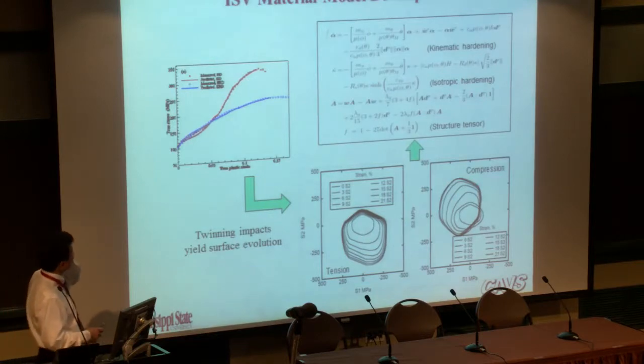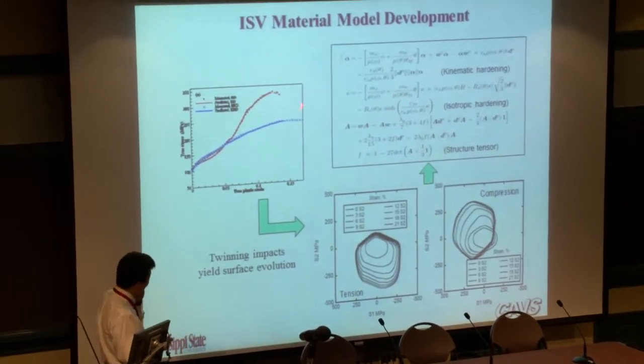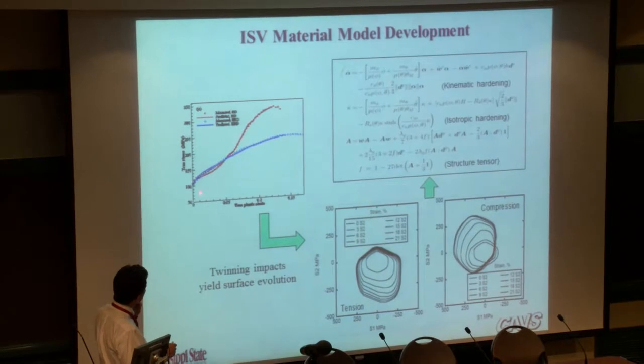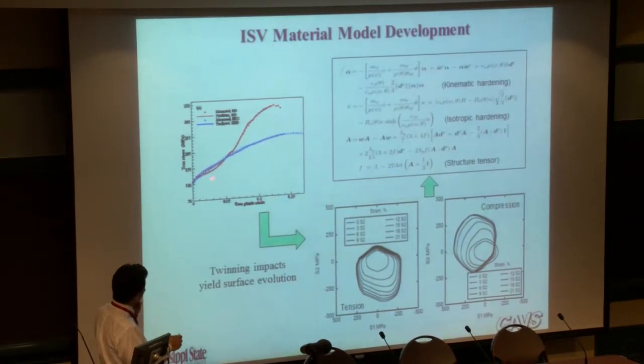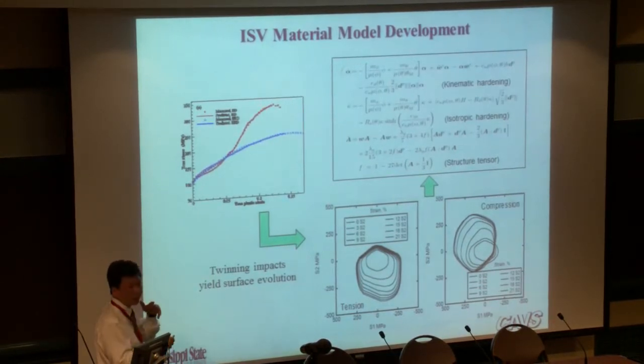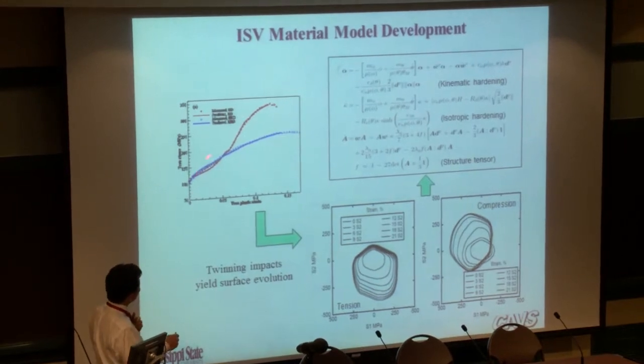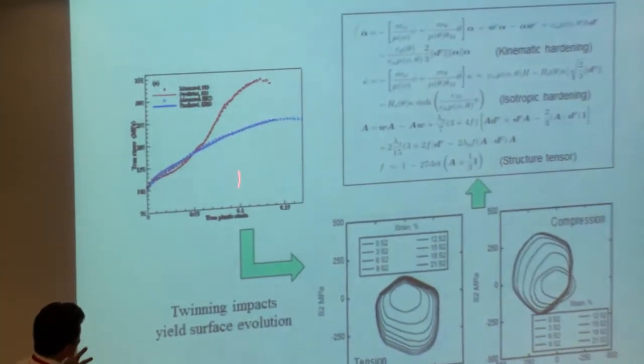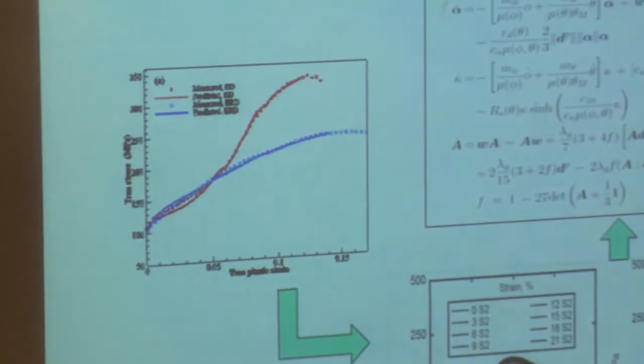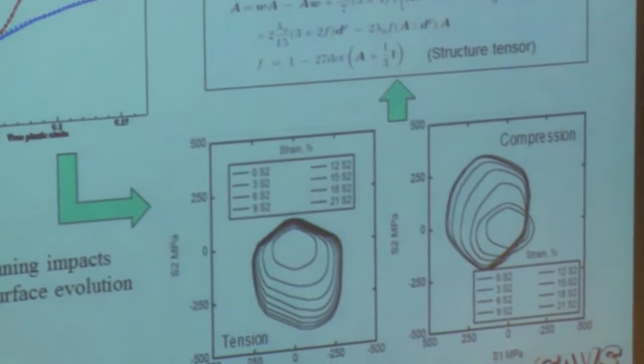This is a typical example showing that in magnesium at a certain temperature and strain rate, there's twinning going on, which will exhaust in a way that becomes a fracture and so on. Then you have the normal stress strain curve. So we're using crystal plasticity and so on to create a yield surface, which will tie in more easily with the numerical code for the finite element approach.